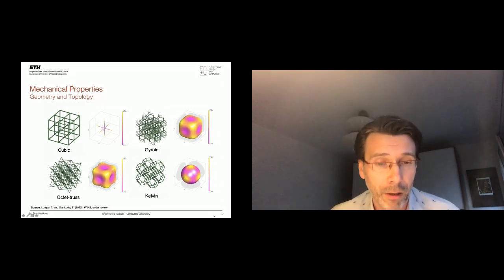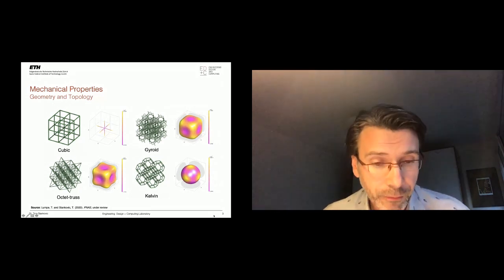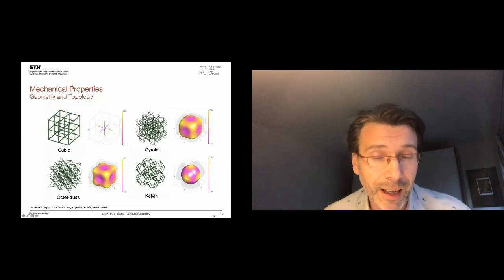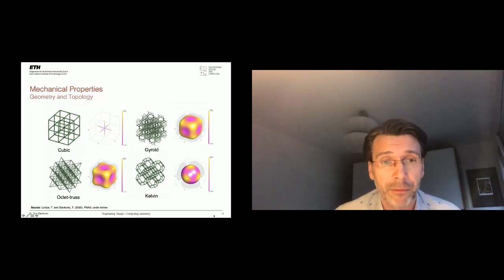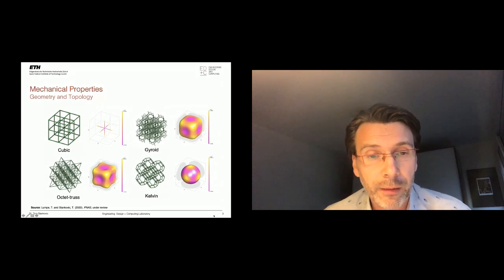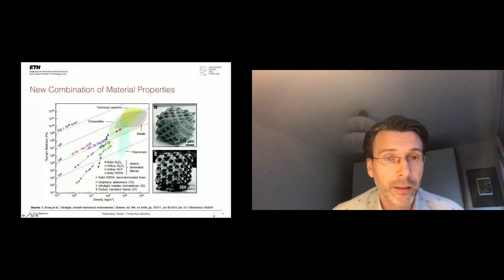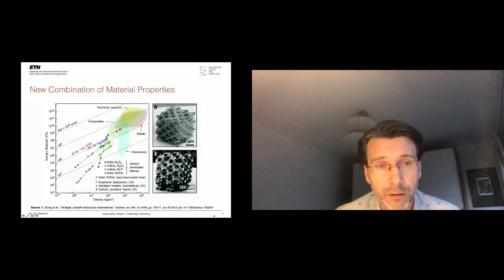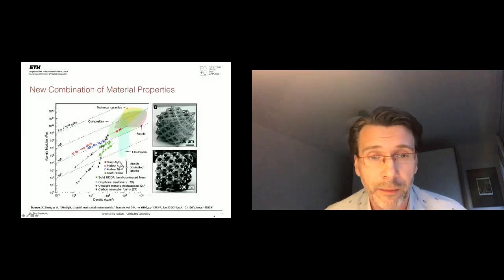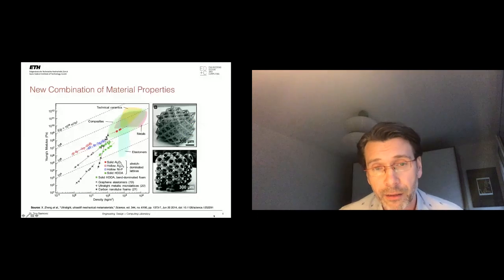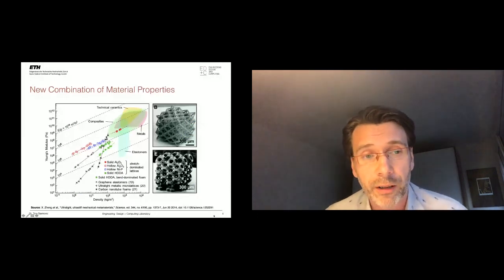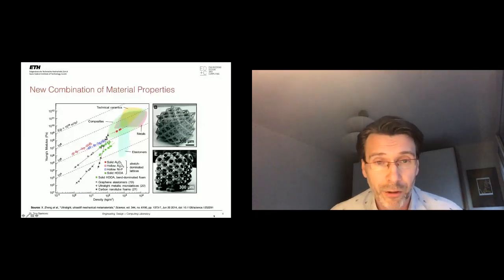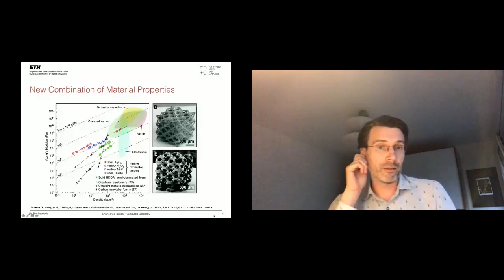That means it's much more efficient and it's light, basically. You can also see that some of the materials retain this property stably. So as you increase the density, the mechanical performance does not change. But for instance, in the case of carbon nanotube foams, you can see that as you reduce the density, the Young's modulus drops significantly. So there are also many pitfalls